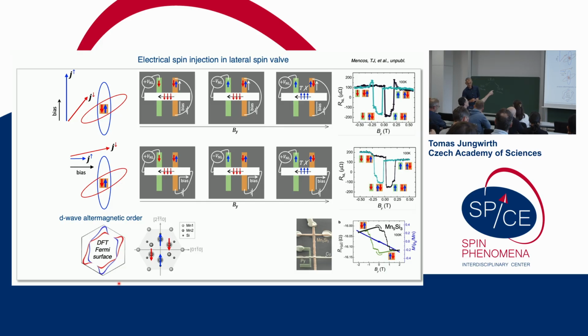Yeah, go ahead. So in this explanation where you draw the arrow representing the bias, normally in the spin splitter context, you would have the current flowing in your altermagnet, and you would generate spin polarized currents. But here the bias is applied across the interface with copper. You mean the top one or the bottom one? Which geometry are we talking about? This one or this one? Let's say the bottom one. The bottom one, okay. So you apply the bias between the altermagnet and copper, and what you see then is the splitting of the chemical potential. So the sign of that would be a representation of the spin asymmetry and the spin injection, which is actually an out-of-plane process, where current is injected in the z direction. So how is that related to the sign of bias in the plane? Isn't that different? Yeah, it's a very good question.